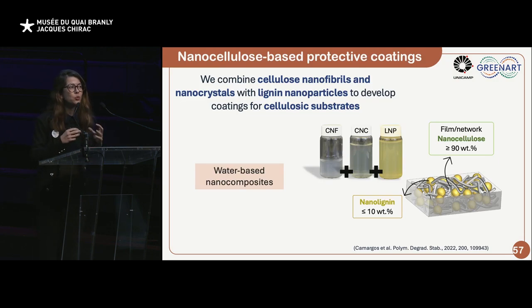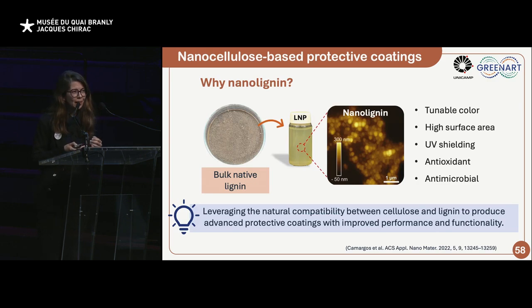So we combine these three types of nanoparticles to produce a water-based nanocomposite. And in these nanocomposites, the nanocellulose forms this network, the film network, representing up to 90% of the dry weight of the coating, while the nanolignin corresponds to up to 10% of the coating. And why nanolignin? Is not lignin the bad guy, right? So